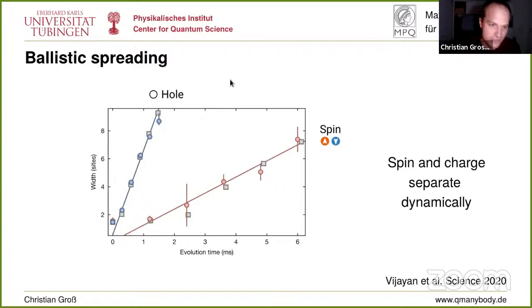And of course, we can also show this. This is now tracking the width of those distributions you have just seen in this 2D plot versus time. And you see the fast hole and the slow spin here. You see really that those 2 excitation wavefronts of the spin and the charge dynamically separate.